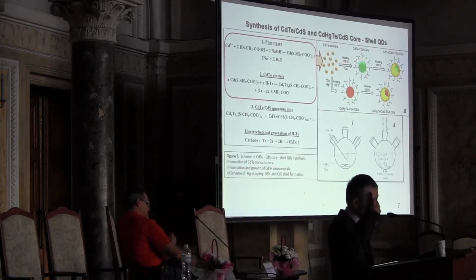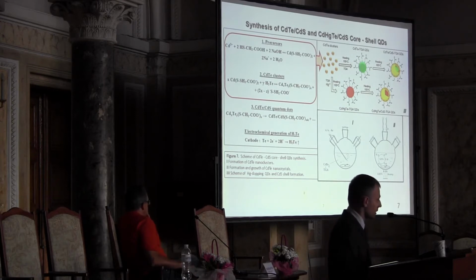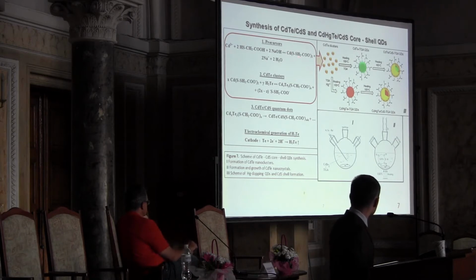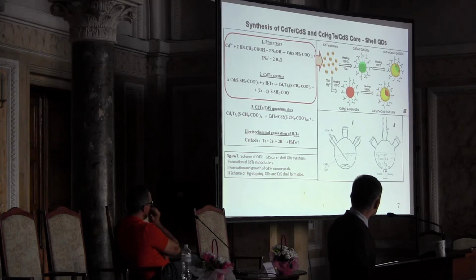And the synthesis we use to create cadmium telluride quantum dots was actually developed in the mid 90s. The idea is that you use the cadmium salt in the presence of thiols and basic conditions. Firstly, you create the complex of cadmium with thiols. And then you inject the tellurium source, and it can vary. It can be either H2Te gas purged through the solution, or, like here if you can see, you can create sodium tellurides or sodium polytellurides and add them. And just an exchange reaction happens, and you get the core of cadmium telluride stabilized by the thiols, and because of this charge, they're quite stable, and because this bond is quite strong, basically covalent, the system itself is very stable.